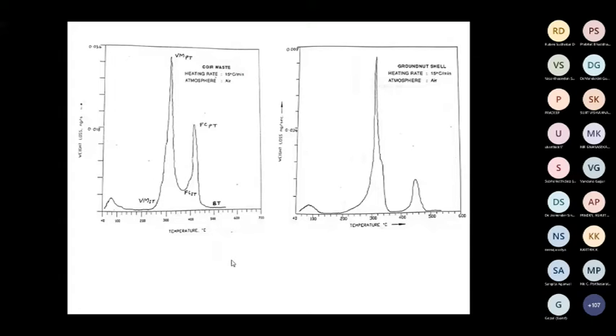So the first one is for coir waste. I have not shown TG here, only the derivative thermogram. That is of our interest. I have shown here all the derivative thermograms of the 7 biomass fuels. This is for coir waste. Here you can see two sharp peaks. The first, initial peak is a very small peak, we forget it. These are the two characteristic peaks for coir waste. Heating rate is 15 degrees per minute, atmosphere air. For coir waste, this is the profile.